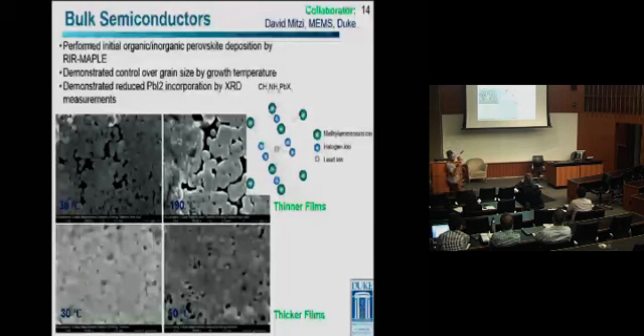And so we've just started very preliminary studies looking at perovskite deposition by RIR-MAPLE. So looking at things such as the impact of the thickness of the film and also the temperature of the substrate during the deposition to see how we can control the perovskites.